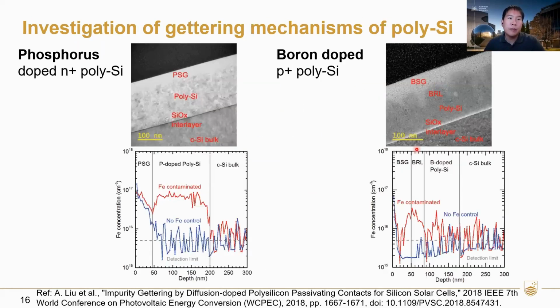Next, we also use SIMS to study the gettering mechanisms of polysilicon. On the left here, we have a phosphorus-doped, N-type polysilicon. On the right, it's a boron-doped, P+ polysilicon. We have two samples here. One is intentionally contaminated with iron. One is a control, a float zone clean wafer. By comparing the two, we can identify where the iron is concentrated.